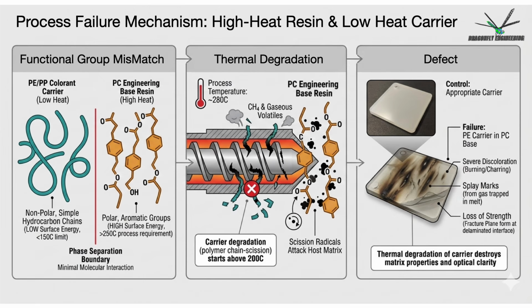There's also a chain scission matrix attack that occurs. So if you process at 280 C, the polymer chains start to scission in the polyethylene carrier, which starts at about 200 C. You get volatile off-gassing of methane and other gaseous stuff. And there's also a chemical chain reaction where the free radicals that come off of the degrading polyethylene will start attacking the polycarbonate matrix, degrading the base polymer structure.